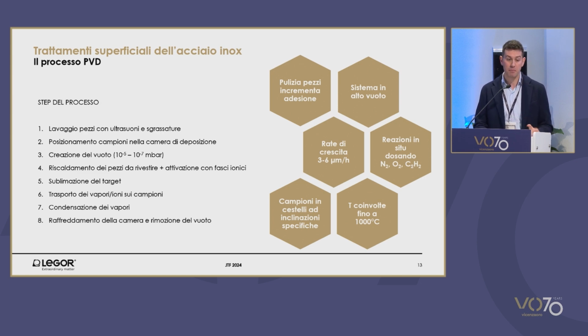Vacuum is generated with pressure equal to 10^-5 and 10^-7 millibar. The target is transformed into vapor, and the metals are then deposited on the substrate. Afterwards, the chamber is cooled down. With these systems, at times you can have reactions with the deposition of the metal together with gas, which is not inert but reactive, as in the case of nitrogen, oxygen, or acetylene. You might create on the substrate carbides of the metal